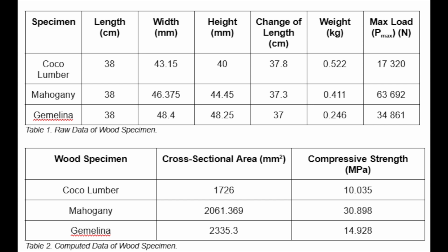Based on the National Structural Code of the Philippines and the Bureau of Product Standards, mahogany meets and even exceeds the expected compressive strength value, typically 15 to 30 MPa for structural timber, making it acceptable for structural use. Gmelina falls within the acceptable range for light to moderate applications, while cocoa lumber at only 10.035 MPa falls below the minimum structural standard and is more appropriate for non-load bearing or temporary use.